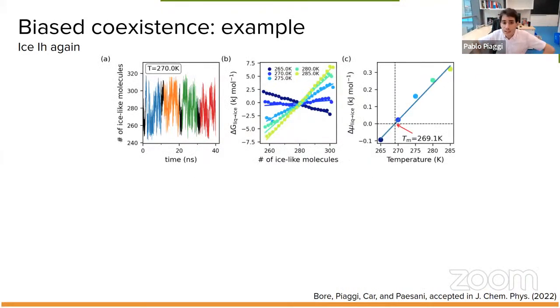Okay, so this is, again, some results for ice Ih. What we're doing here is creating a bias potential that samples the number of ice-like molecules between two values. In this case, it's around 250 to 320. That's essentially the formation of one full layer. We're doing this with four multiple walkers.